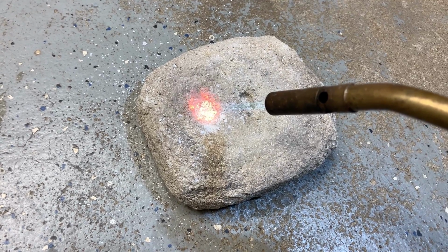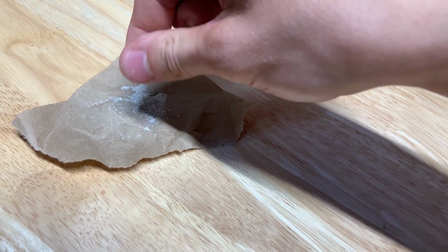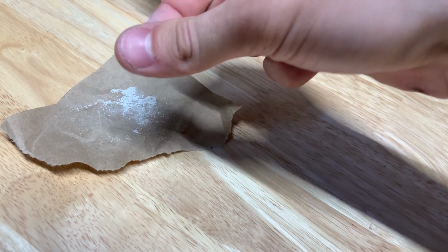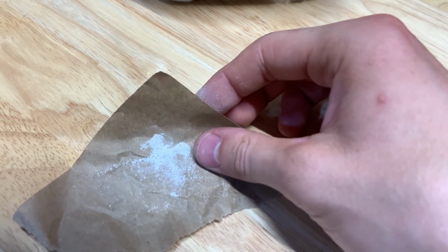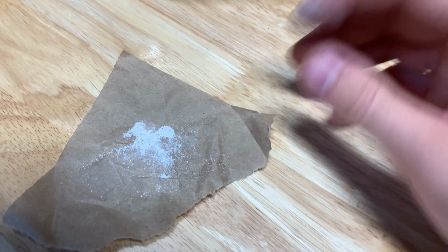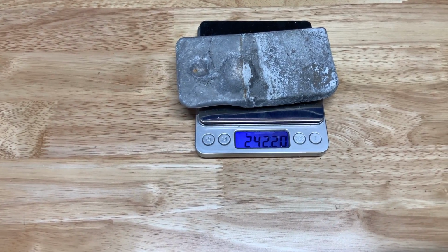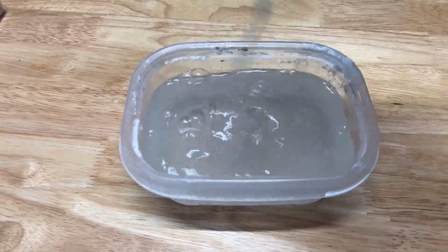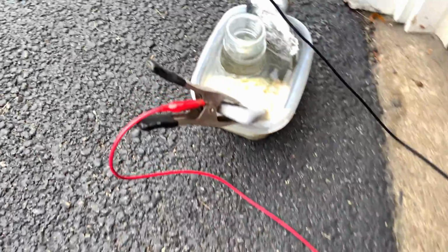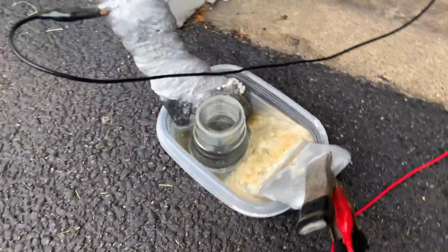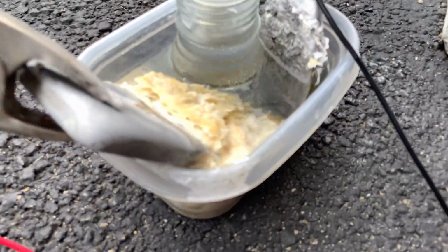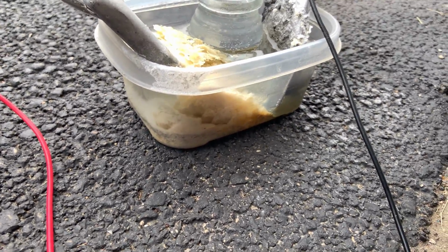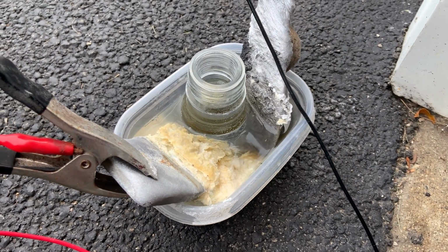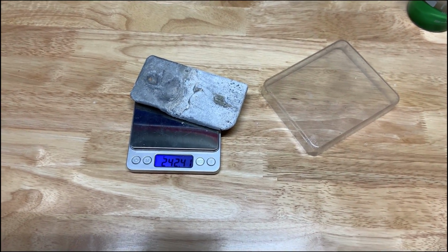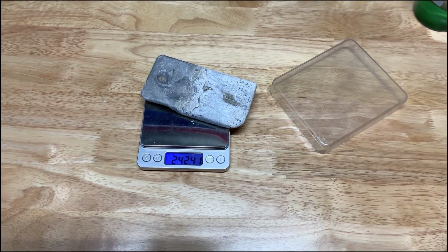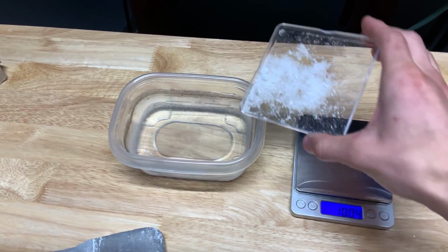and then I tried feeling the powder afterwards between my fingers to see if it felt like aluminum oxide, but I couldn't really tell, so I decided to see if the actual electrodes degraded at all, so I weighed it before, I did another run, and I weighed it after, and it ended up being the same weight. You can see all of the yellow flakes instead of what should be mostly white or gray from the aluminum hydroxide. So from this point I realized that I was using way too much Epsom salt. So after the ingot weighed the same, I dialed it way back to about 5 grams for this run to see if it would degrade at all.